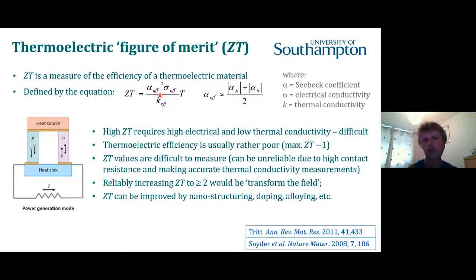And one can see that if you can push the electrical conductivity and the Seebeck coefficient up to get high numbers, and you can keep the thermal conductivity low, then the ZT value should be high, and that would be favourable for thermoelectric efficiency. The problem is that the electrical and thermal conductivities tend to increase or decrease together. So if the electrical conductivity goes up, the thermal conductivity also goes up. So that's one of the key barriers to increasing the thermoelectric efficiency.